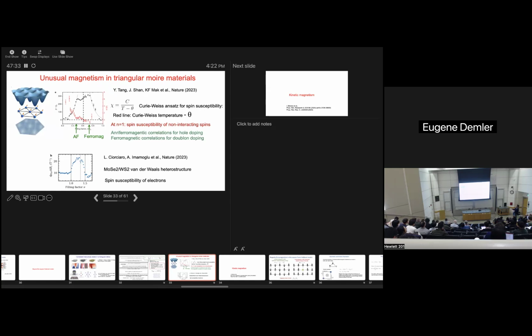Then, when they dope, in one case they get antiferromagnetism. In the other case, they get ferromagnetism. So somehow magnetic interaction is switched on by doping, which is the opposite of what we saw in the case of square lattices, where magnetism gets suppressed by doping. Here, it only appears because of doping. And even more surprisingly, it changes sign depending on how we dope.